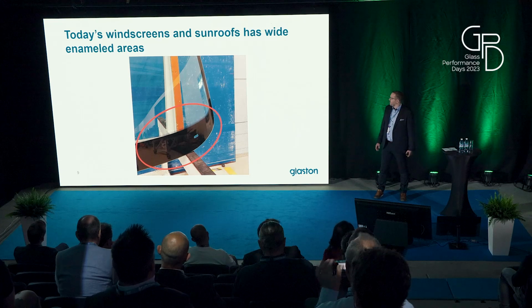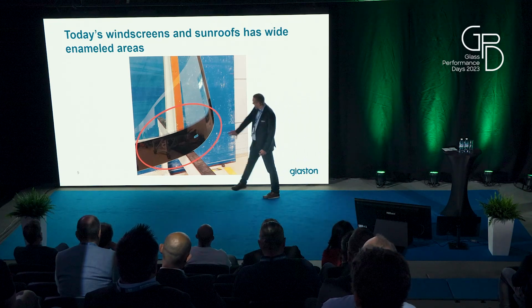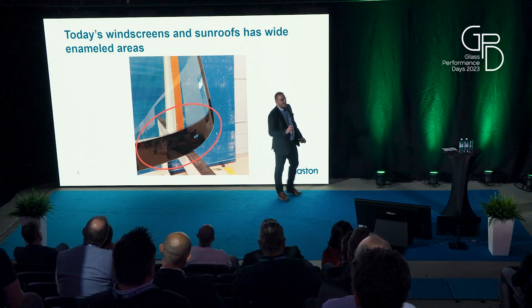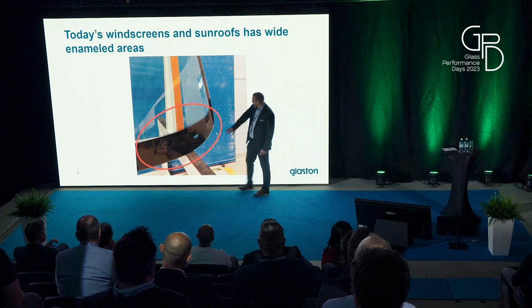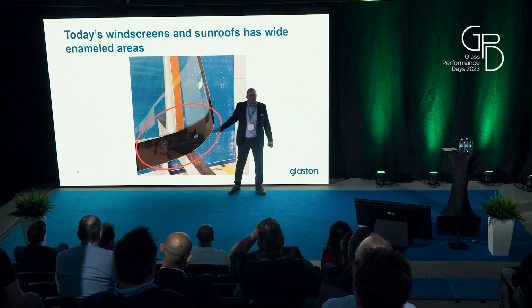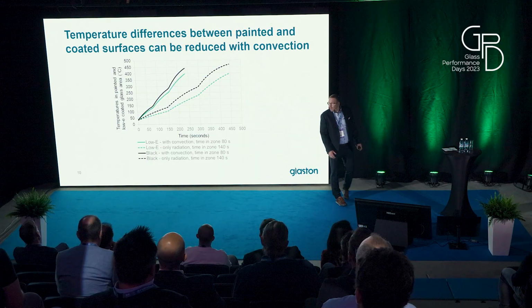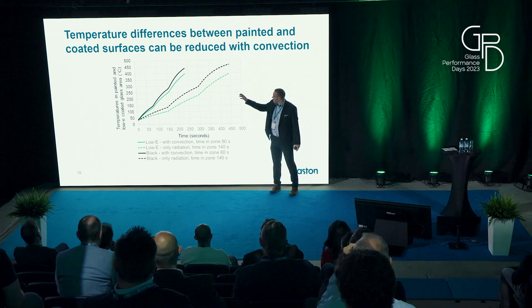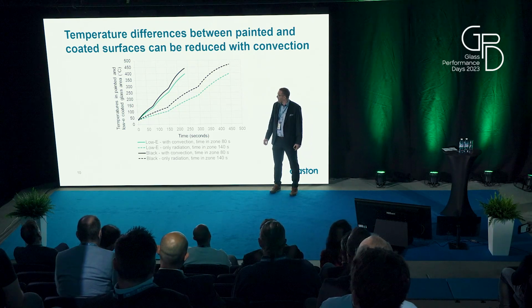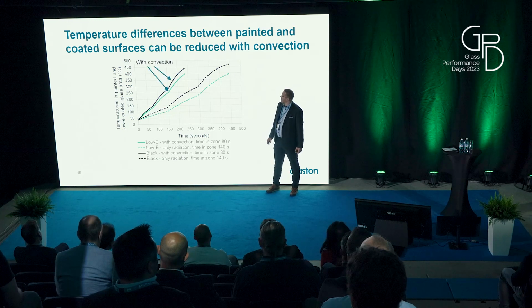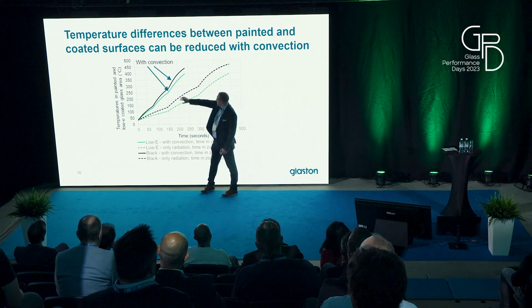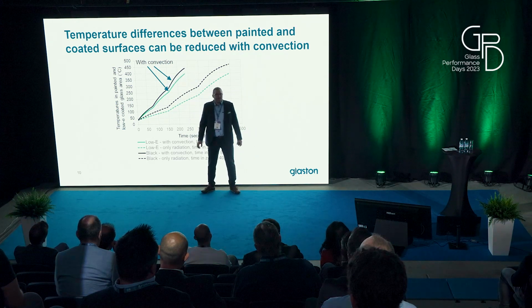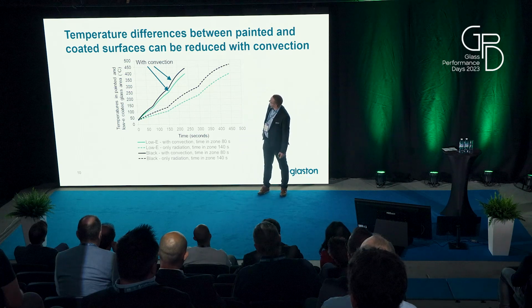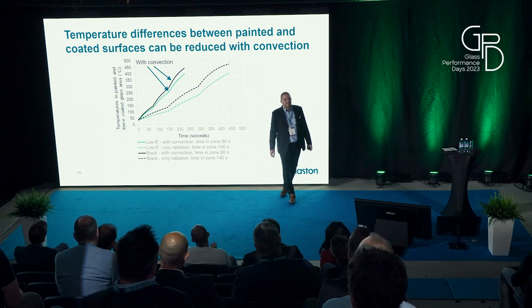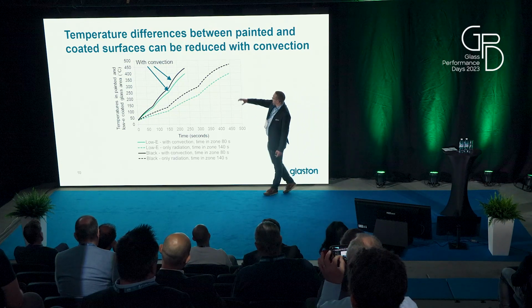Here is one example. There is a part of a windscreen. There is a white painting, a 10 centimeter wide area. And heat transfer in these areas and clear glass areas in heating with radiation is different. Here is an example. Green lines are with the low-e coating, and the black lines are with the radiative heating. So if we are looking at convection, you can see that this temperature difference between painted glass and coated glass is just at the end maybe 40 degrees. So it's good comparing to what we get with radiation.